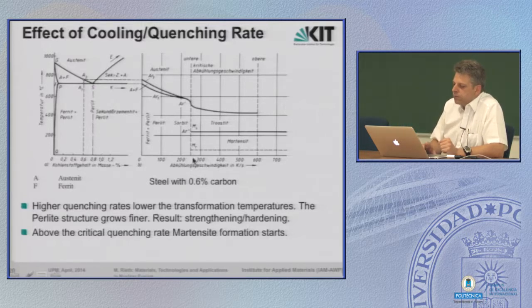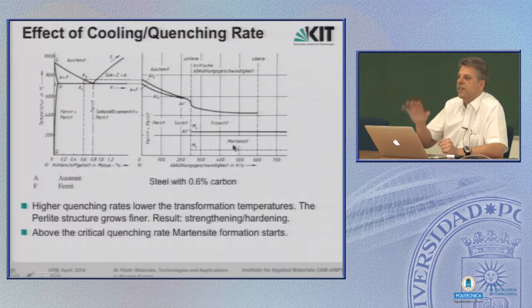But then, if we go even to higher cooling rates, more than 250 Kelvin per second, this transition line goes even further down, but then you see there is the appearance of another transformation line. And this is the critical cooling rate to produce the Martensitic structure. We will go much more into detail later on. As for now, it's enough to say there is still another phase called Martensite or Martensitic phase, which appears only if you cool down fast enough.